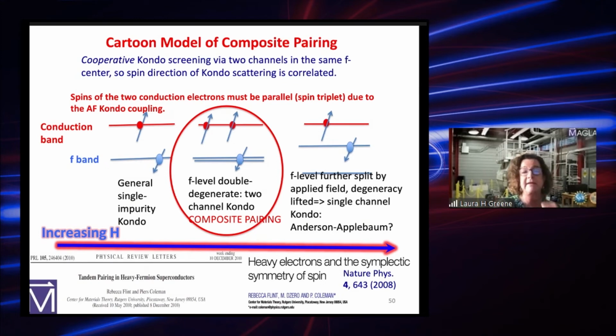Now let's apply a field. As you apply a field, you start breaking this degeneracy. So this Kramers doublet will start to split, and now you go back to the single impurity Kondo. You don't have that degeneracy anymore, and that splitting should grow linearly since it's Zeeman splitting. And so what's interesting is that unless you have some kind of pairing, whether it's coherent or incoherent, you don't see this Kondo scattering, this linear increase of the gap with applied field.